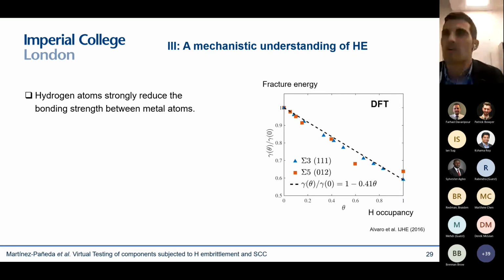And there are three aspects that I think are key to explain our rationale. The first one is that when you do atomistic calculations, DFT or molecular dynamics, what you see is that the fracture energy or the atomic bond energy is significantly reduced with hydrogen occupancy. These are some results for nickel. And you can see here fracture energy versus hydrogen occupancy. And you see that if your, let's say, grain boundary is full of hydrogen, occupancy of 1, then you have a 40% reduction in that bonding strength, in that fracture energy. So the grain boundary strength is going to be 40% weaker if you're full of hydrogen.